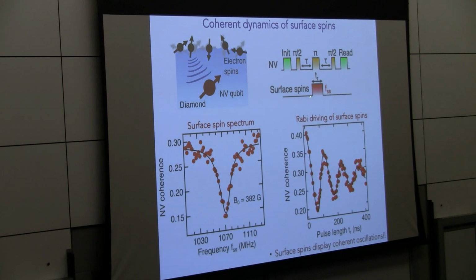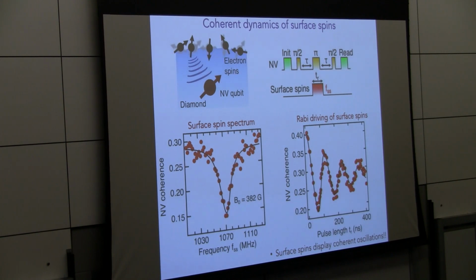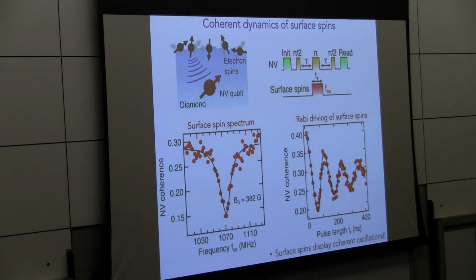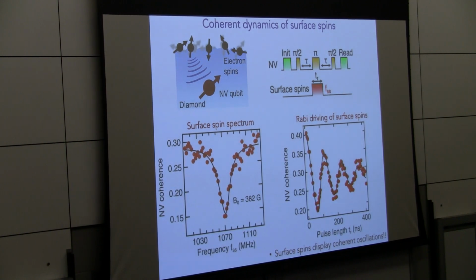And that's what we've done here using what's called double electron-electron resonance, where we use the NV center as an optical readout to probe the frequency spectrum and the dynamics of the surface spins. This is a pretty powerful use of the NV center, by the way, because now we're able to read out spins on the order of a handful of spins, which are nominally dark, and we're able to use the NV center as a window into their dynamics.